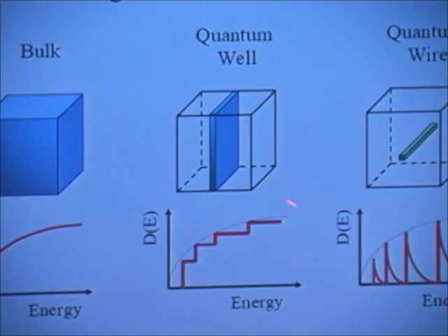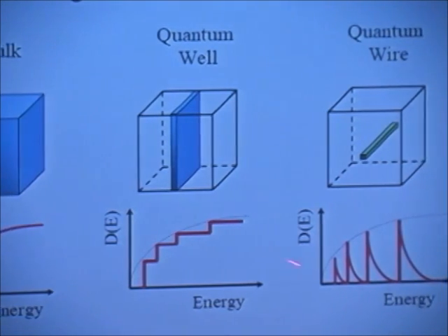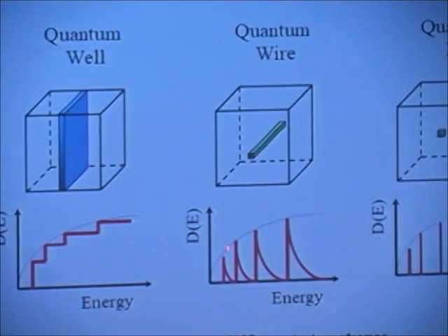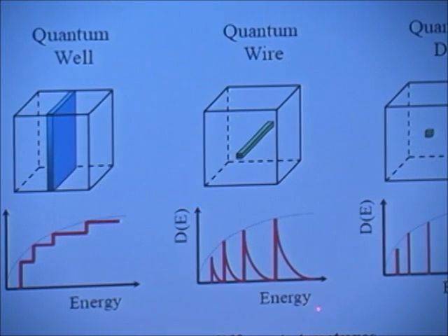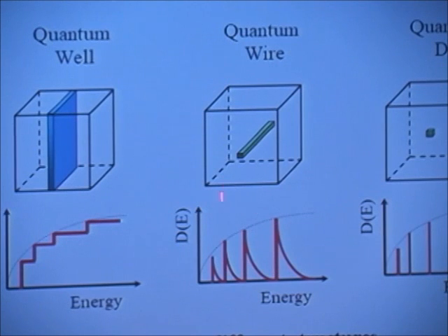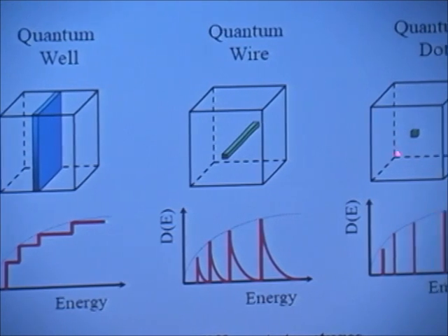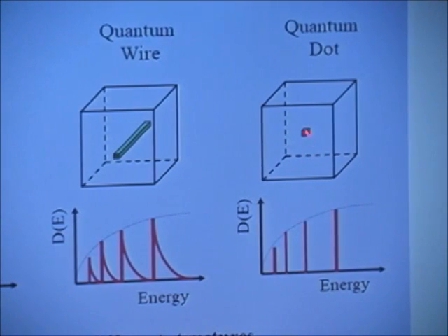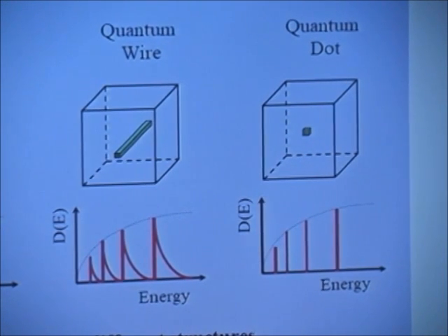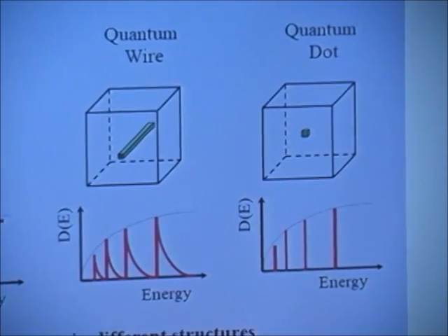1 dimension is very different indeed. It's very strange. You get a series of levels like this. So in other words, at the lowest energy, the density of states reaches a maximum and then decreases as we increase the energy. And this is a quantum dot, which is where the electrons are quantized completely in all 3 dimensions, and you just get a series of discrete lines. And we will look at all these things in due course.